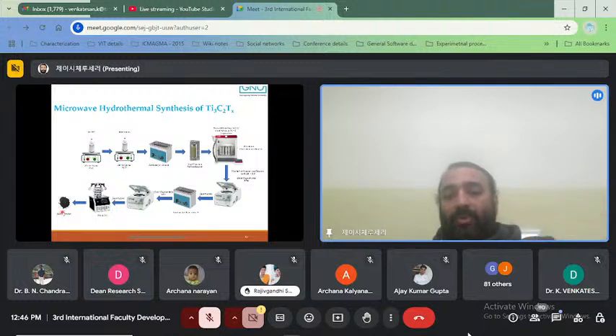So if you need more yield, of course you need to take the bottom part. But if you need a very small yield with a small number of layers, then you need to go for the supernatant. That is the technique. As I discussed before, these are the elemental mapping images for the titanium carbide MXene. You can see that besides titanium and carbon, here you have fluorine, chlorine, and oxygen. These terminal groups, fluorine and chlorine, come from the hydrogen fluoride, HCl, and lithium fluoride. These chlorine and fluorine groups hinder the electrochemical performance when we use it in a battery or supercapacitor. So this is very important.